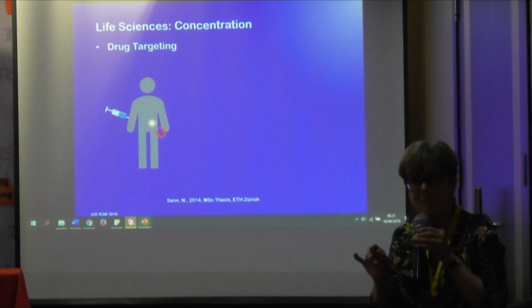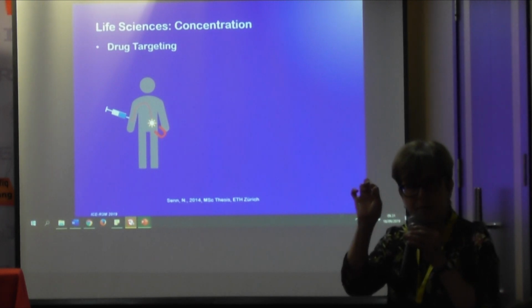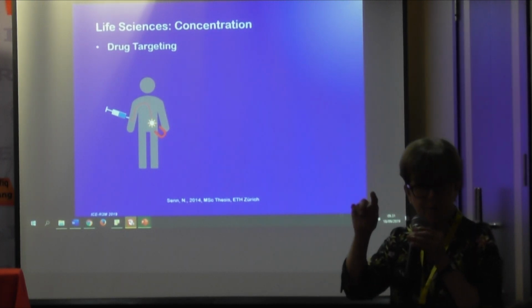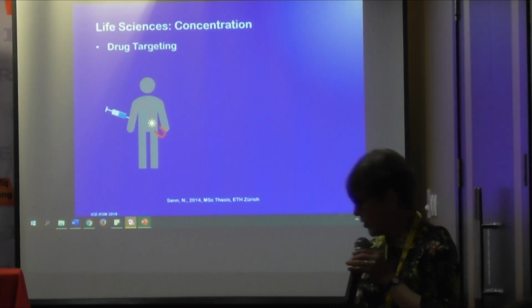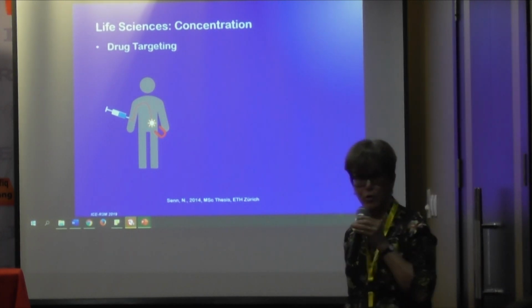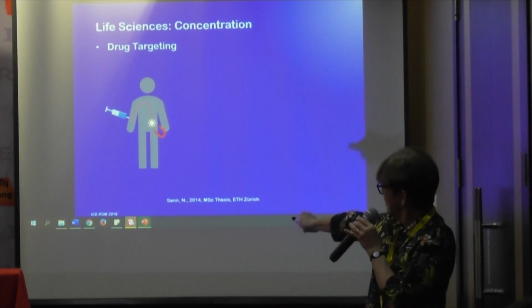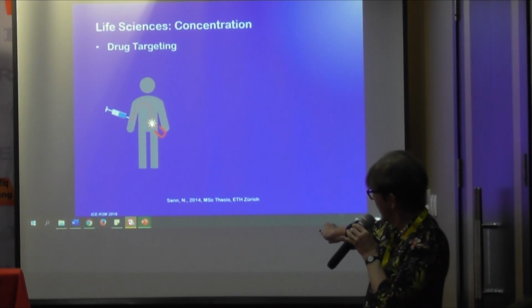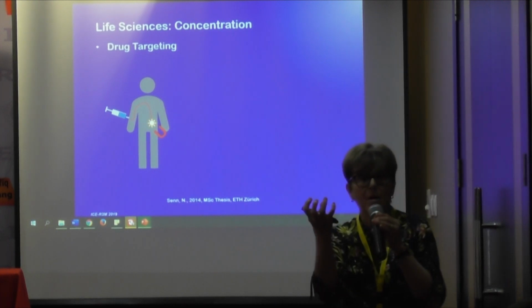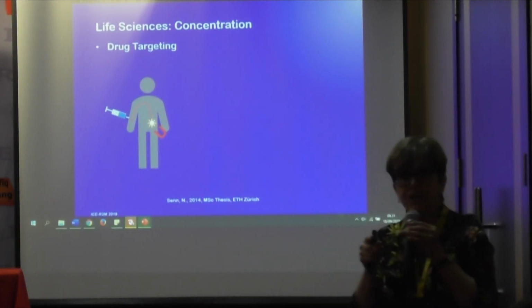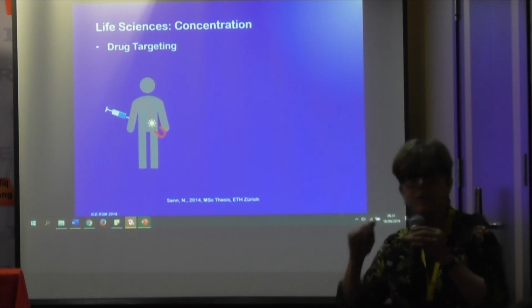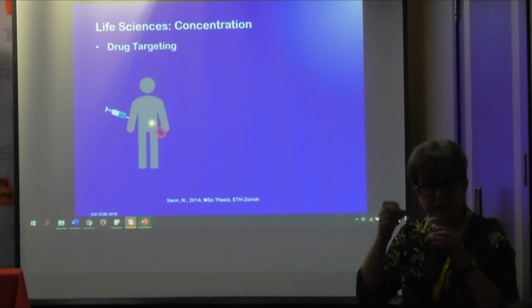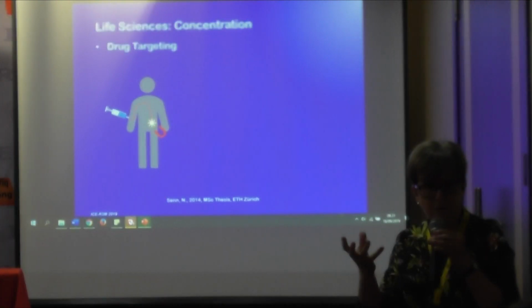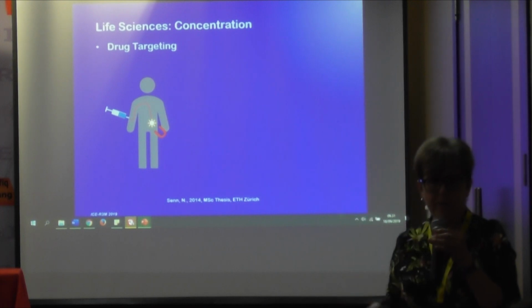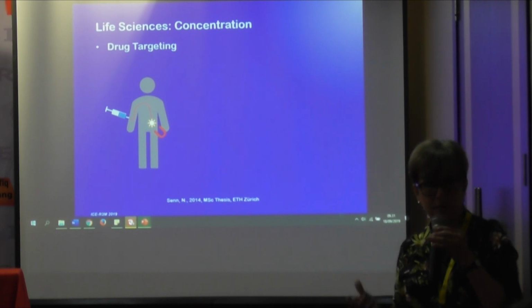But what happens if you take a magnetic nanoparticle and coat it with the chemotherapeutic material, and then you put a magnet close to the area where the tumor is? When the drug goes through the bloodstream, it gets captured more by the tumor. This has the advantage that you can use less of the drug than if you just let it circulate by itself. And that's less toxic for the body, because that's the problem. These drugs are highly toxic.